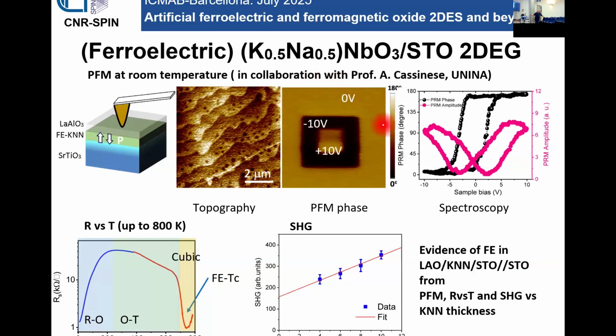And you can also see that without applying the gate voltage, essentially we have the same phase as having plus 10 volts. So this means that the polarization is pointing down, the spontaneous polarization, which is the condition which favors the formation of the electron gas. Then you can, for example, do some local spectroscopy. You see the classical loop that suggests the system is ferroelectric.